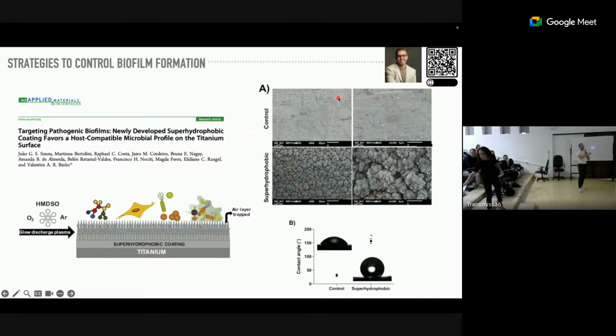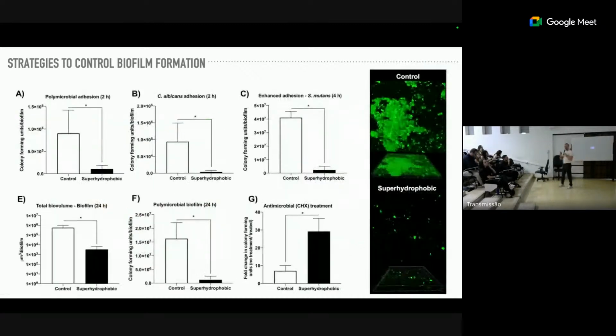So as you can see here is the control, no surface treatment, and the superhydrophobic surface treatment. As you also see, the contact angle between the surface and the water is higher than 150 degrees, which means that the surface is superhydrophobic. In this paper, we're going to see several cellular experiments, but my focus here is the biofilm. As you can see here, we use a model that tries to resemble the composition of a complex biofilm. We are not using one specific bacteria species, we are using a polymicrobial biofilm. So here there is no biofilm because there is no adhesion. As you can see, the control has more adhesion of this polymicrobial species.